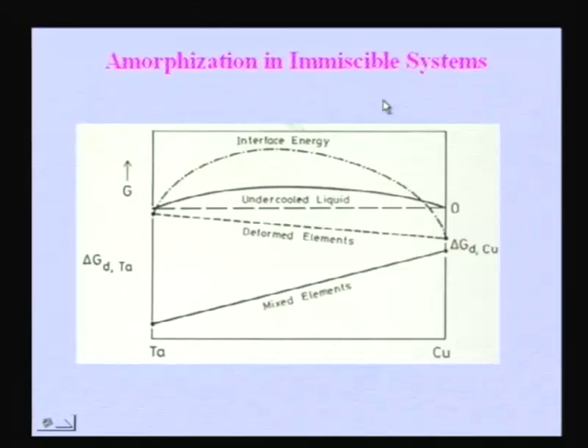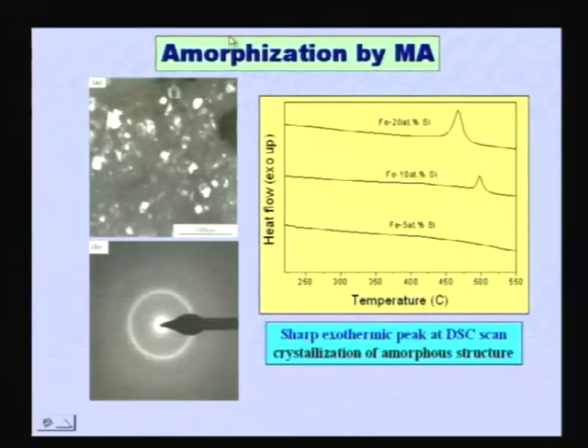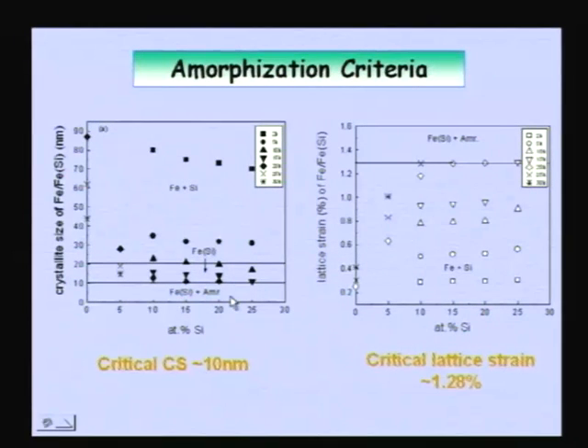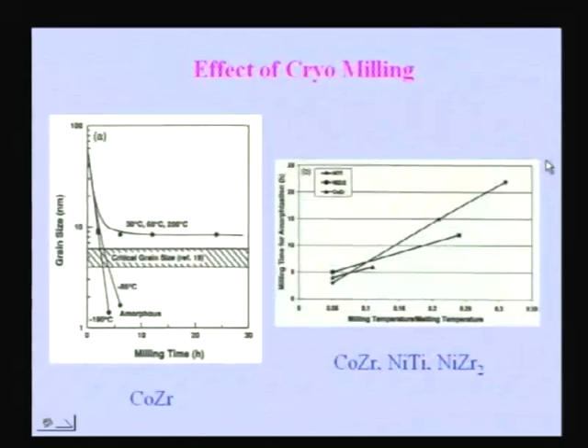This is not possible by rapid solidification, and one can have amorphization by mechanical alloying below a certain crystallite size. We have seen this before. When you bring the nanocrystals below a certain size of about 10 nanometers or so, suddenly it becomes an amorphous phase, and similarly beyond a certain strain it becomes an amorphous phase.